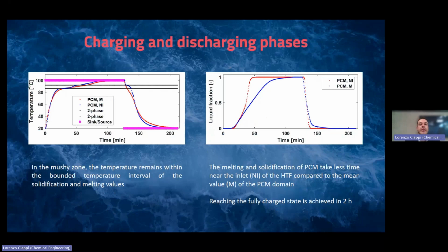During the discharge, the PCM releases sensible heat to the heat transfer fluid initially. It reduces its temperature, solidifies, and then again the temperature of the PCM reduces until reaching the equilibrium with the sink. The analysis was done considering both the average value of the temperature and liquid fraction of the PCM in the entire domain and near the inlet. It's visible that near the inlet, the melting and solidification of the PCM requires less time than the average value of the entire domain.